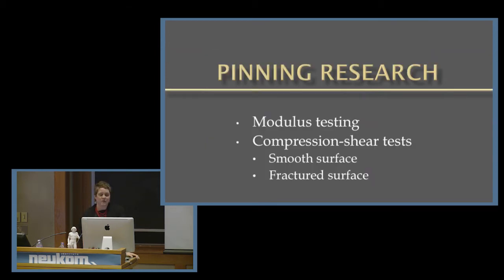We also did a lot of pinning research. I'm going to go over this really quickly too, but it was done in several phases, over a period of about 5 years. We did modulus testing, where we looked at a lot of different pinning materials just to compare their stiffness. And then we did compression shear tests, which were marble cores cut on a 45 degree angle and then pushed to failure.